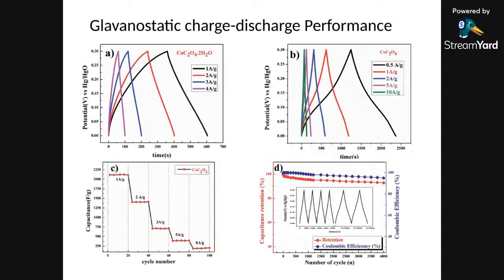So then we have done this charge discharge. If you see the cobalt oxalate hydrated, this total time is around 600 seconds. However, for the same anhydrous material, the charge discharge has gone up to more than 2200 seconds, at a half ampere per gram current rate, which is a very good current rate. So even if you see the total charge time, it is close to 1000 seconds. If you convert that, it means we are close to 15 to 16 minutes of charge discharge.